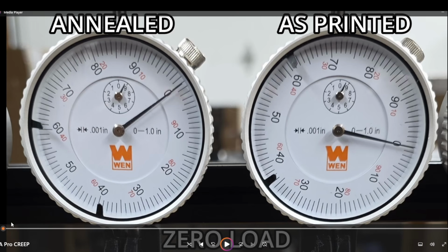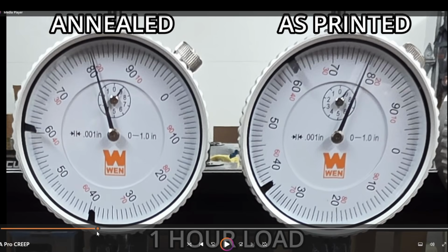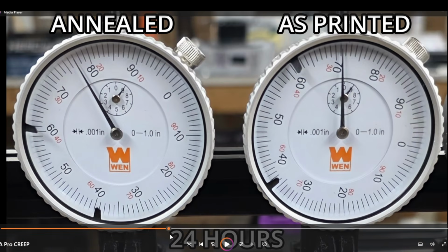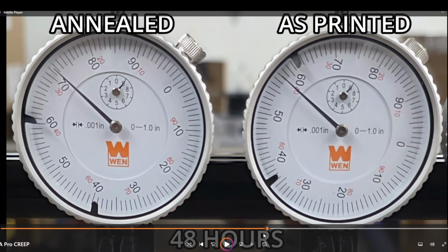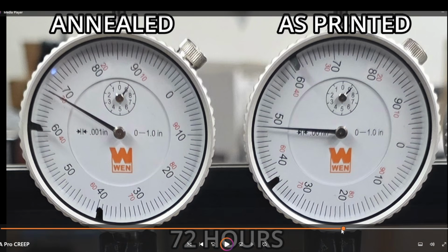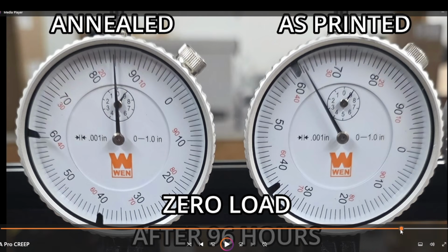This is when I zeroed them out after I loaded the pieces in here. This is immediately after hanging the weights, or 1 hour after hanging the weights. And after 1 hour, the annealed deflected 19 thousandths, the raw deflected 22 thousandths. 24 hours, the annealed deflected 23 thousandths, the raw deflected 29 thousandths. 48 hours, the annealed was 28 thousandths, the raw was 42 thousandths. 72 hours, annealed is 30 thousandths, raw is 52 thousandths.